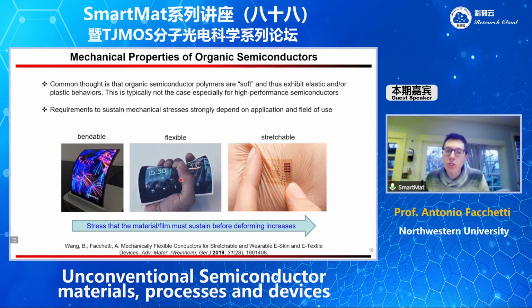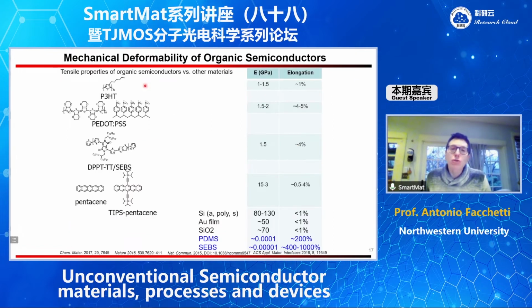Also, what is very important is we talk a lot about flexibility and stretchability, but the requirements are very different if you simply bend the semiconductor or the device once, versus if you flex it many times or stretch it. So the demand is quite different in terms of mechanical compliance. Just to give you a flavor, this table shows some of the Young modulus and the elongation at break. So this is the crack onset for some examples of semiconducting polymers and small molecules. And these are the numbers.